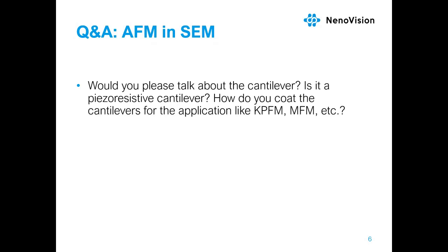And then for MFM measurements, we actually use modified Akiyama probes, which are based on tuning fork, and we deposit a piece of iron on the very end of the tip. So I think the diameter is like 20 or even less nanometers. So then we are able to make very precise and high resolution MFM imaging. But there are plenty of different types of cantilevers according to the specific method which we want to use.